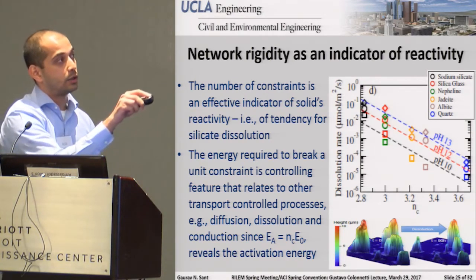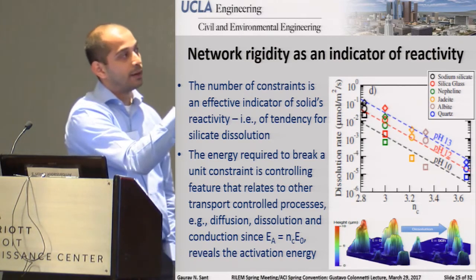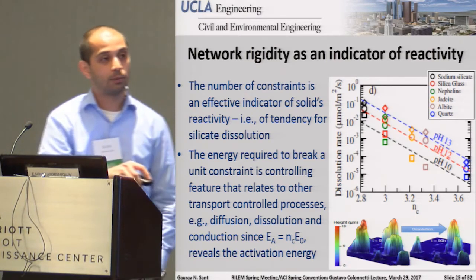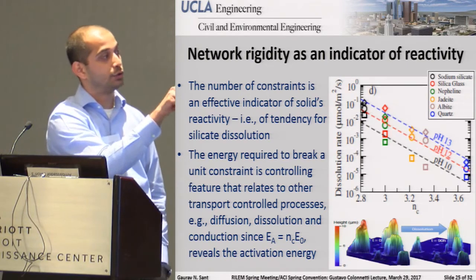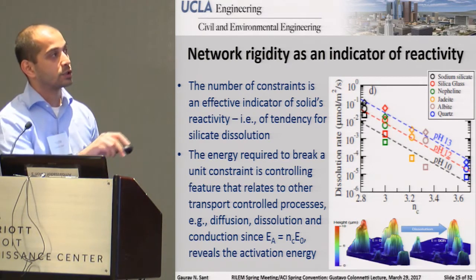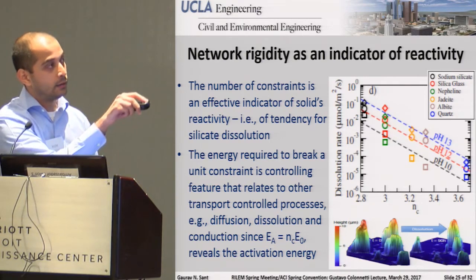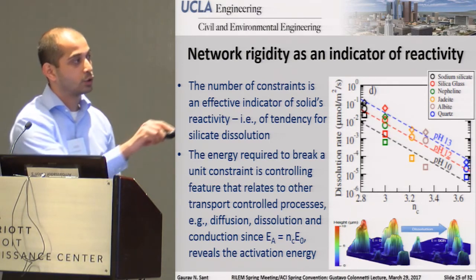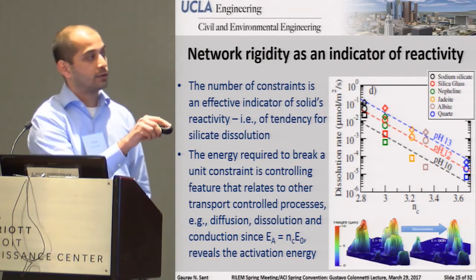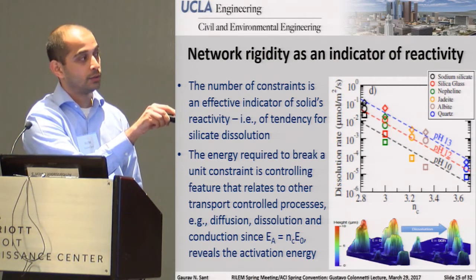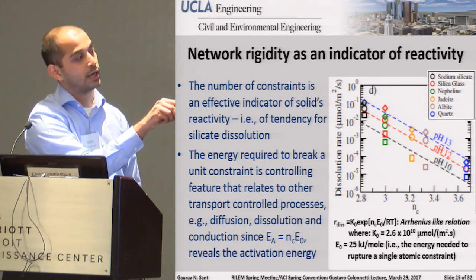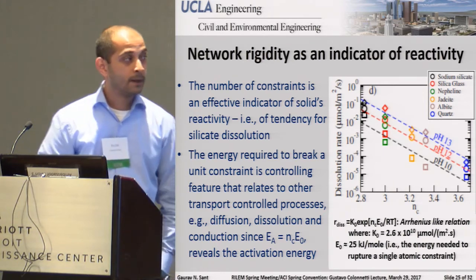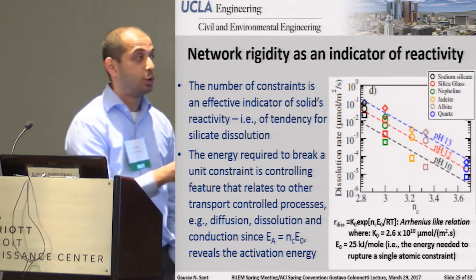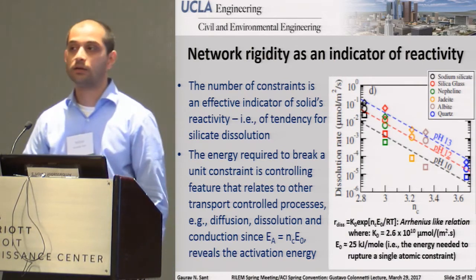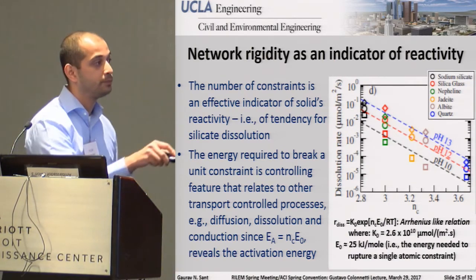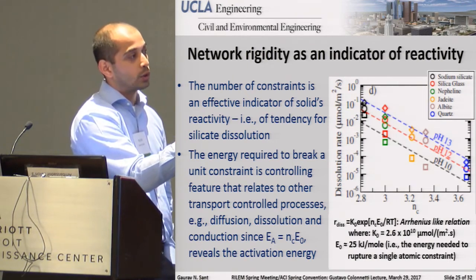The interesting thing that you can start to tell is that you can get perfectly exponential dependencies. You can see that this is a semi-log plot, so you start to get exponential dependencies of dissolution rate and the number of constraints. Now, the reason that this is quite good is what you're really seeing, this trend, is defined by an equation where the dissolution rate is a function of an intrinsic dissolution constant and an exponential term, which has the number of constraints and a number E-naught within it. What's interesting, or at least to us, is that this is very Arrhenius-like. It looks like a classical Arrhenius relation, where you can start to determine what this E-naught number is.